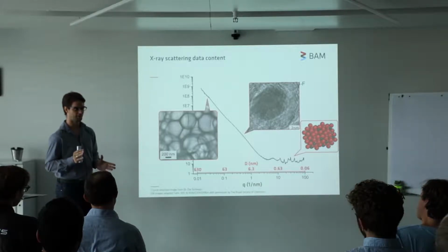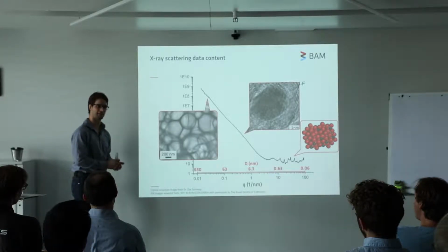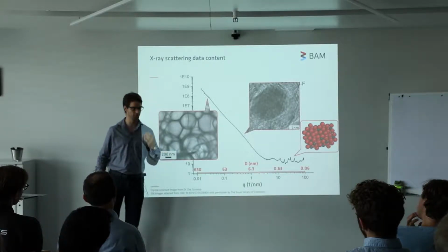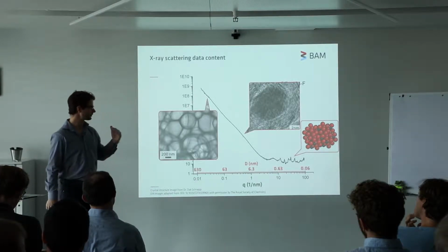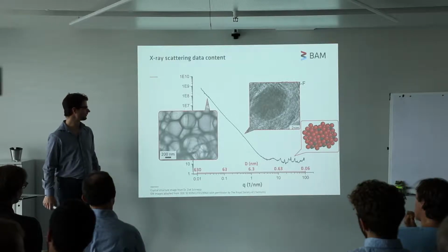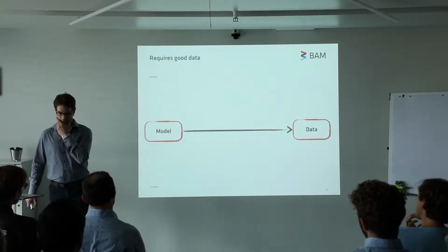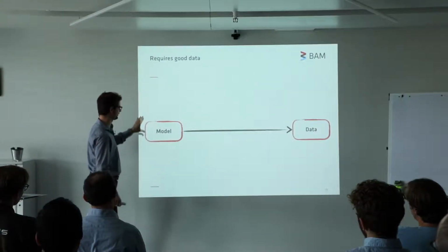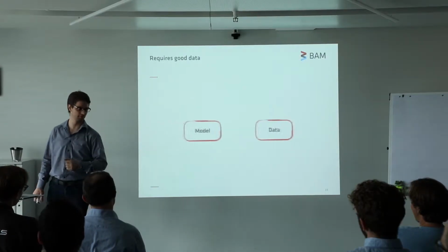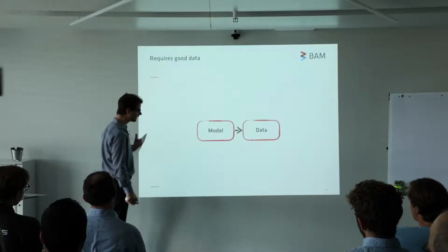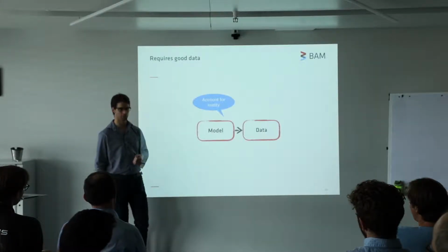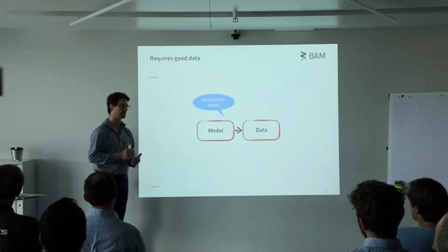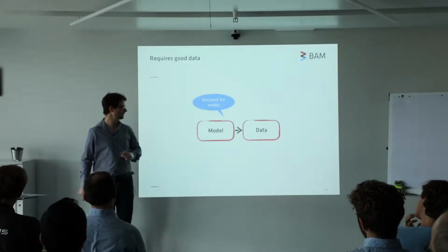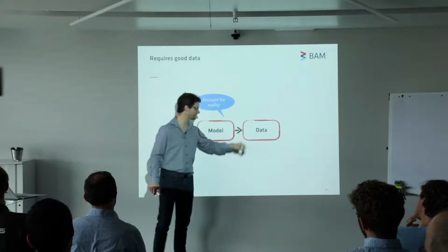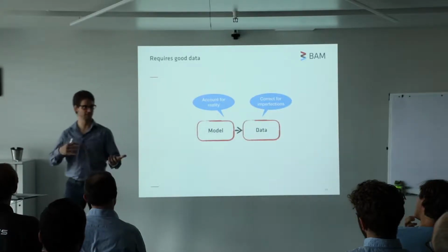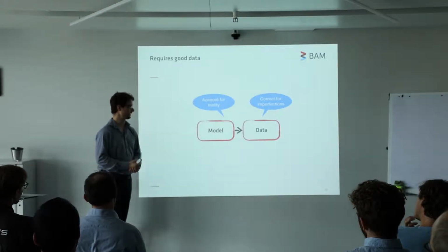However, there's nothing to show that your data corrections haven't been sufficiently accurately done. So it's important for the researcher to do the data corrections to a sufficiently high level that these analyses give the right answer and not just any answer. So that means, in most cases, that we want to fit a scattering model to data, and that, of course, works best if you bring these two as close together as you can. That means that for the model, you want to account for reality. That means including things like beam smearing, beam divergence into the model can be a big step towards matching your data. Likewise, for the data, you want to correct this for any imperfection that you have during your measurements, or at least as far as you can do this.